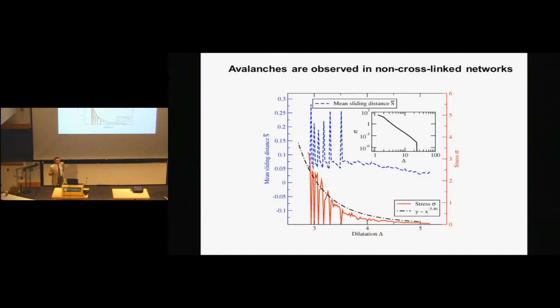What happens? There is no friction. Okay? There are topological rearrangements inside the network. The network is actually just reorganizing as I deform. Okay? So it's another example of a material which has a structure which is basically just evolving during deformation. And any metal does that. Most polymers do this, okay? But this is just a demonstration that fiber networks can do it. So you have large rearrangements corresponding to relative sliding events of fibers and drops in stress. And of course, when you compress sufficiently, then this thing becomes smooth again because essentially the whole thing becomes a compacted material.